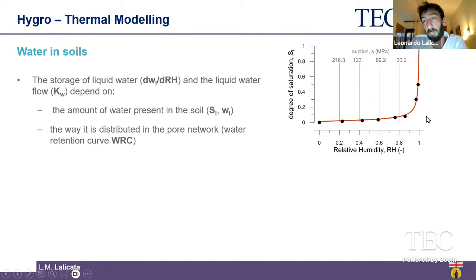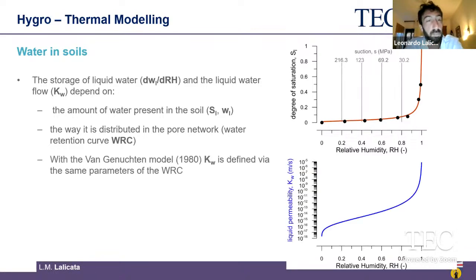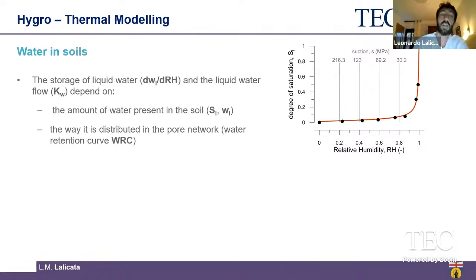So these points here represent experimental points that relate the degree of saturation to relative humidity. And here I have also reported some suction values at some relative humidity values. The good news is that we can fit these experimental points by using a mathematical law, called the Van Genuchten law, that gives a unique relationship between the degree of saturation and the relative humidity.